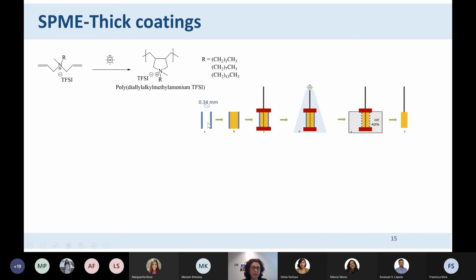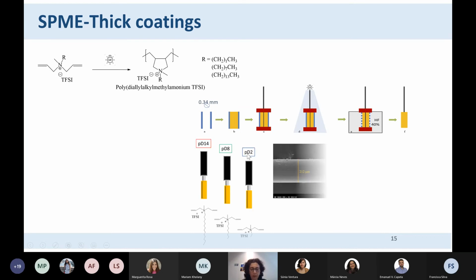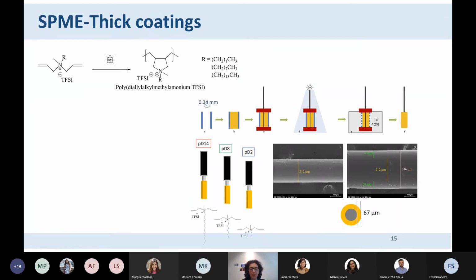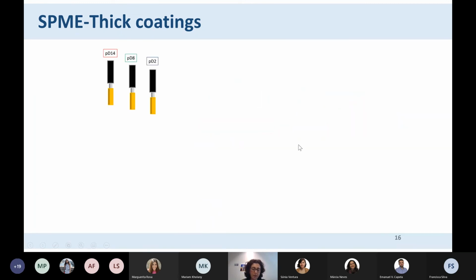So we have this mold, and it is a glass mold. We fill it with the polymer solution, polymer in acetone. We put here what is going to be our handle, and we irradiate it with UV light for a certain amount of time. In the end, we just put this in a solution of HF to dissolve the mold, and we get our fiber. This handle here, how did we get it? We had a couple of colleagues that work on SPME, and we used their used SPME fibers. We just burned the fiber and we kept the handle so that it would fit inside of the GC. So we prepared three polymers, and here are the fibers that we prepared. We have the disadvantage of always having the same thickness because the thickness is controlled by the mold, 67 micrometers.